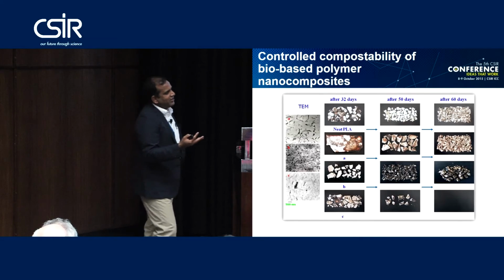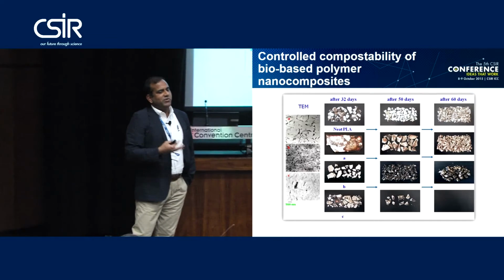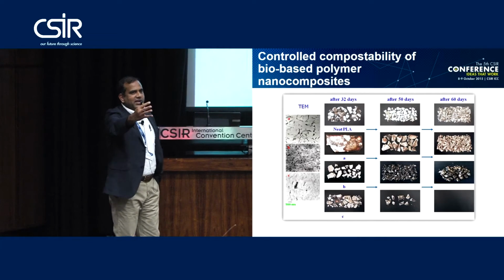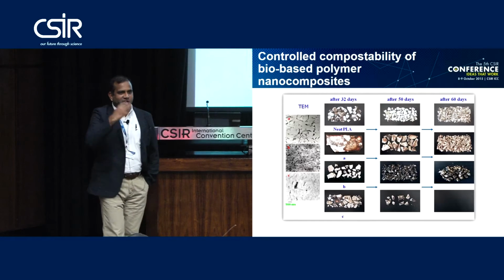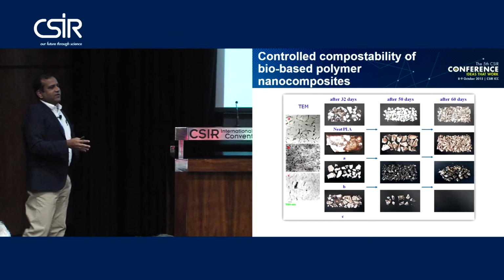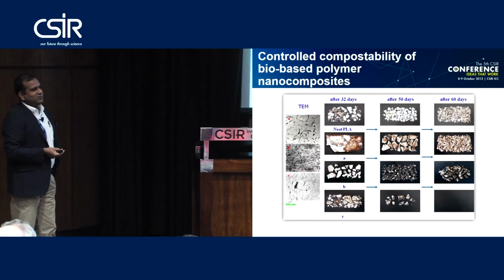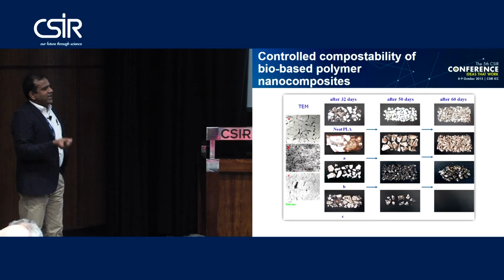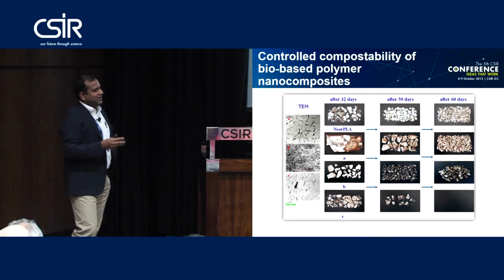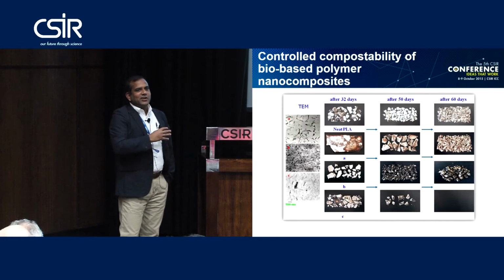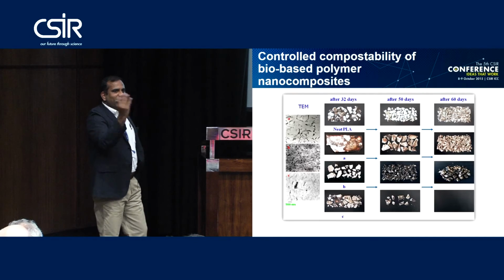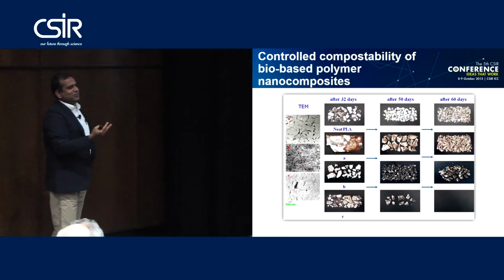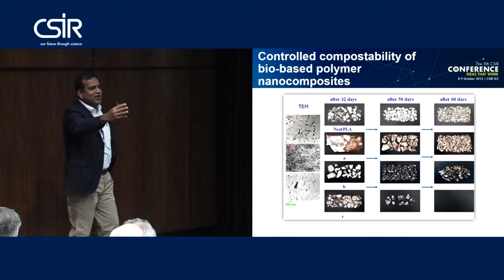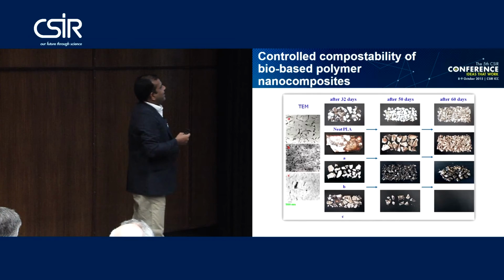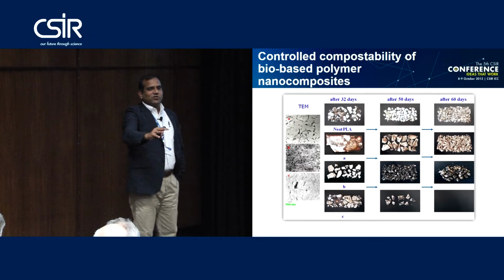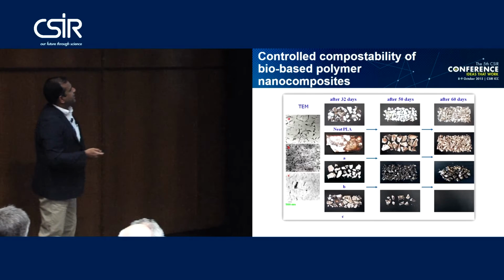For some applications, your bio-based composite must have a longer life cycle. For some applications, you need a much shorter life cycle. Particularly the Prius car, I think that is our research product from Toyota R&D. We developed a PLA-based composite that must have a longer lifetime, so we try to block the polyester using nanocomposite technology to delay the degradation. But for packaging applications, we need very quick degradation, so you can control the degradation.